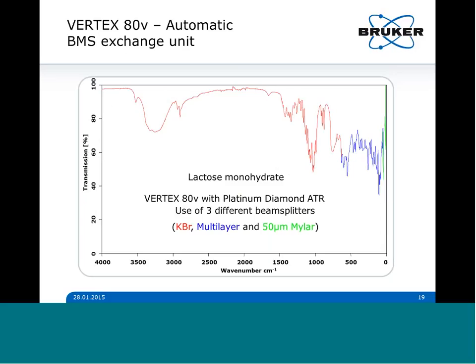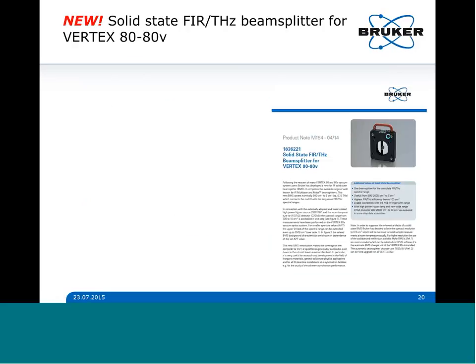And here you see an example spectrum using the automatic beam splitter change unit. We measured lactose monohydrate as an example, using the VERTEX 80v with platinum diamond ATR and 3 different beam splitters. KBr, see here in red, for the mid-infrared, and the far infrared multilayer, and 50 micrometer Mylar. And well, from 4,000 down to 5 wave number.